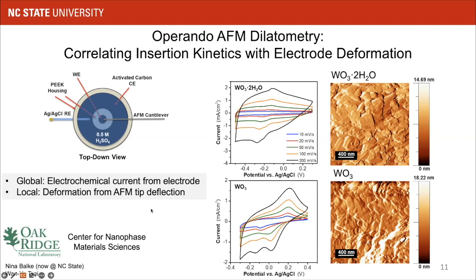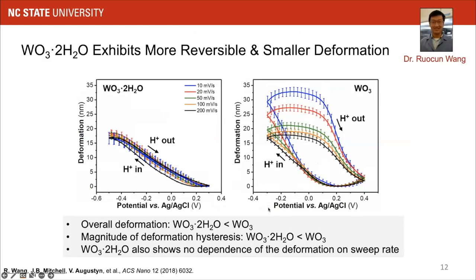And now what we're going to do is just land our AFM tip in the middle of these electrodes somewhere, and then track how that electrode responds when we're applying the cyclic voltammetry signal. And what we saw over and over again was that the hydrous material exhibits more reversible and smaller deformations. So the deformation magnitude for the same thickness electrodes was always smaller for the hydrous material. Very notable, there was a lack of hysteresis. So that's what we mean by reversibility.